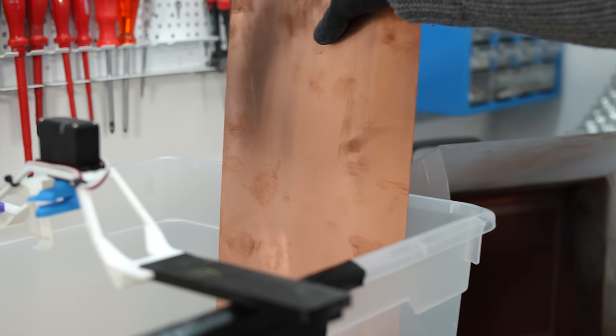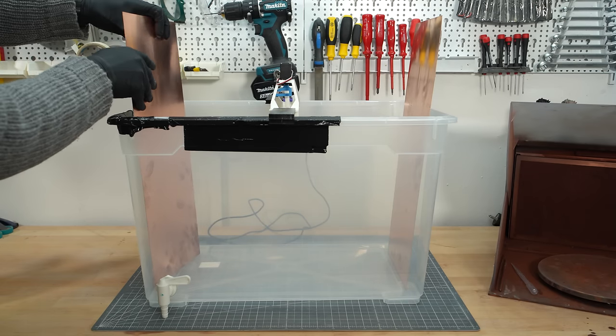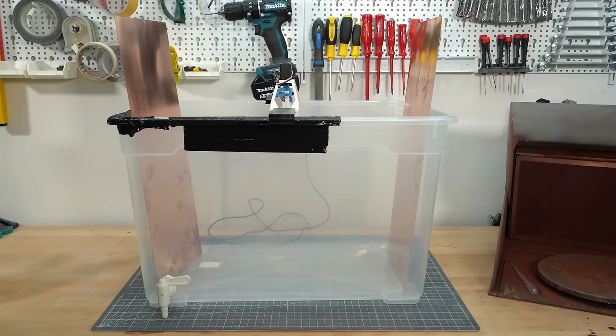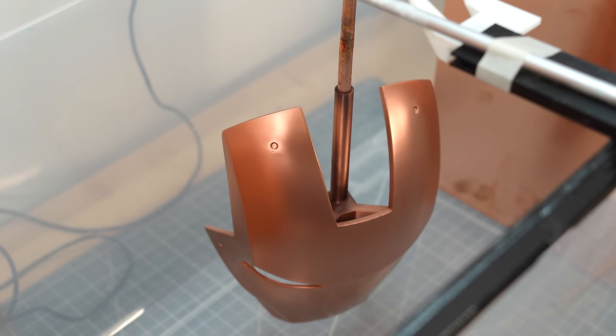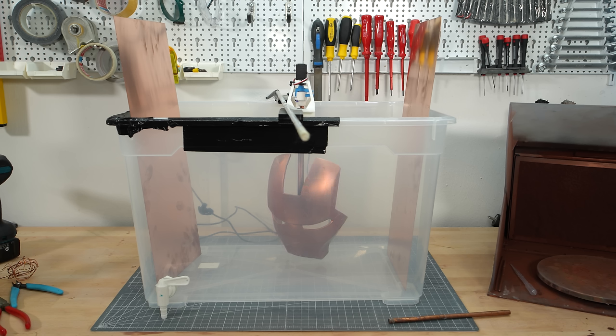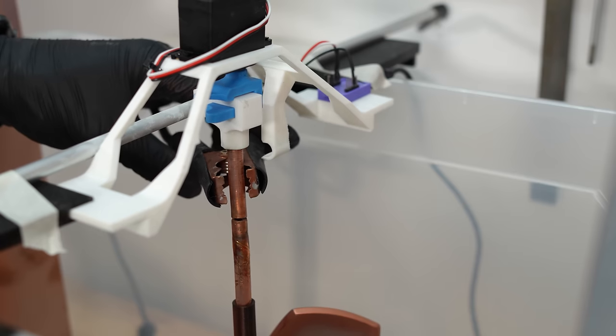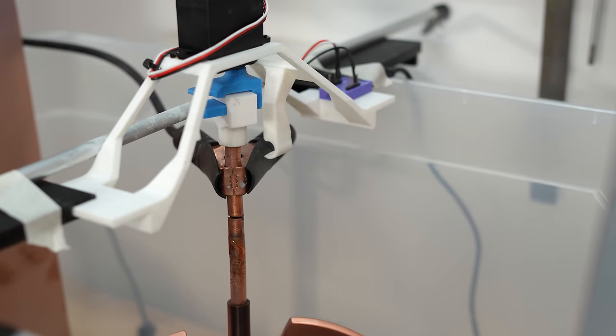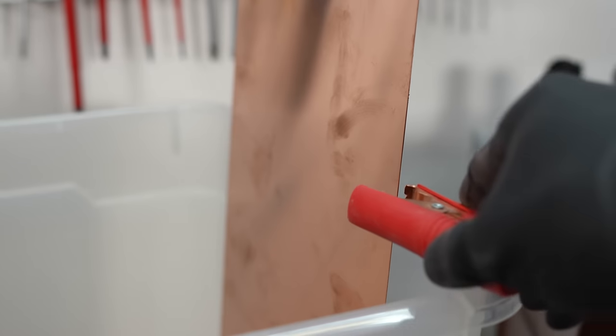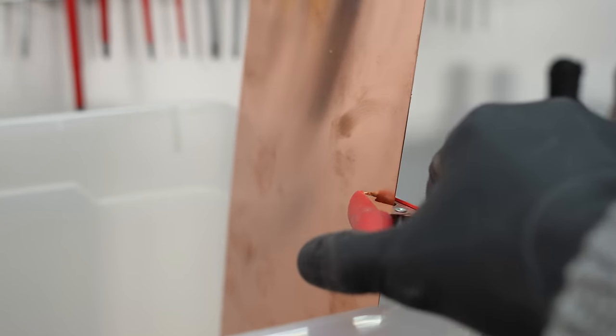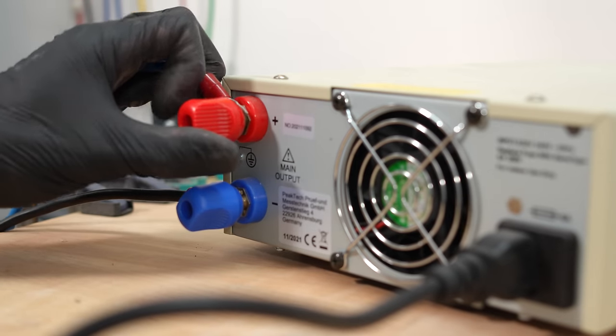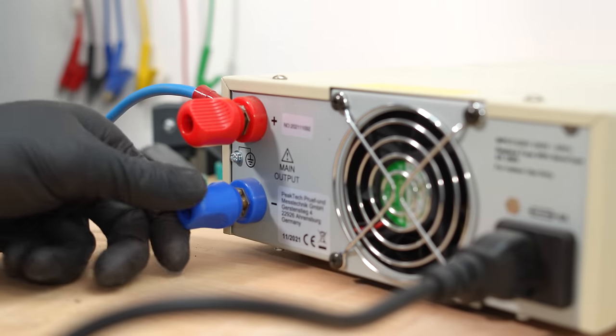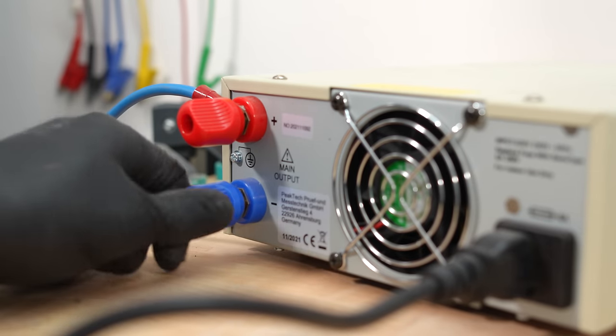I place it on the left and right in the box. Normally, coffee filters are wrapped around it, but the sheets are just too big. The print hangs in the middle of the rotary jig. This is how it looks. The 3D print serves as the cathode and is connected to the negative part of the power supply. The anode sheets are accordingly connected to the positive pole. In a nutshell, as the sheets dissolve in the acid, the copper ions are deposited onto the 3D print through the electric current.